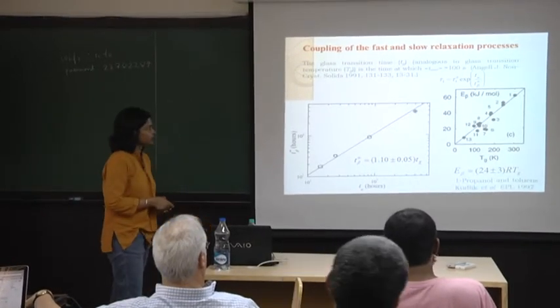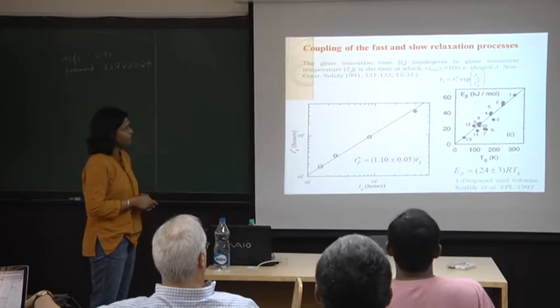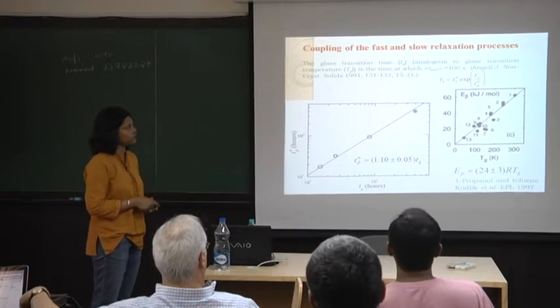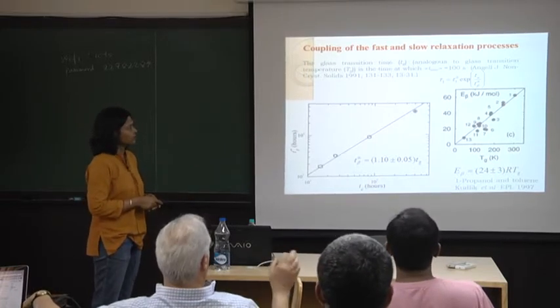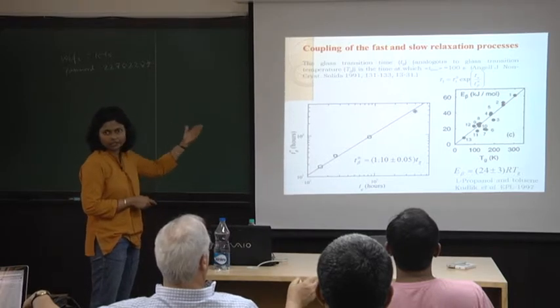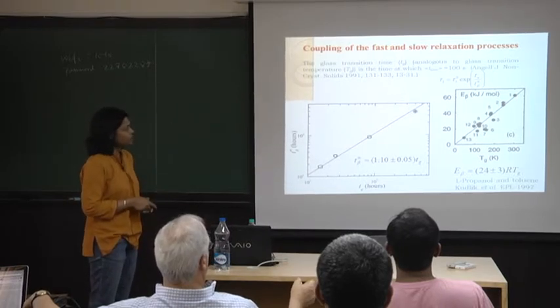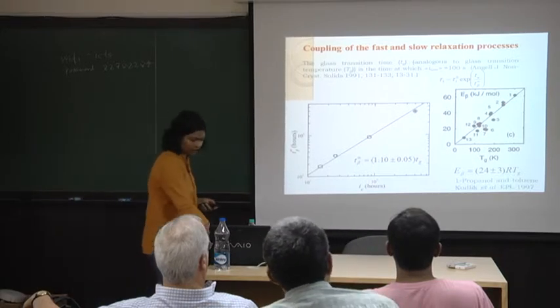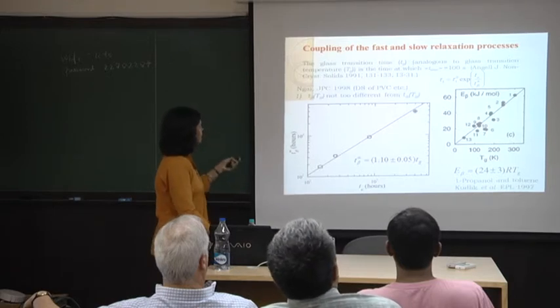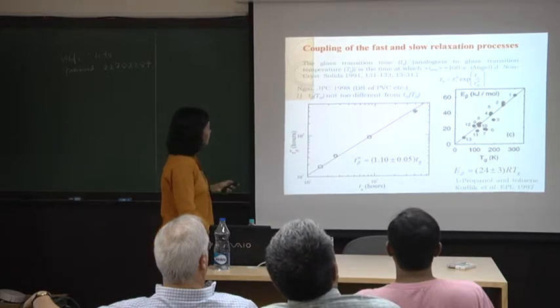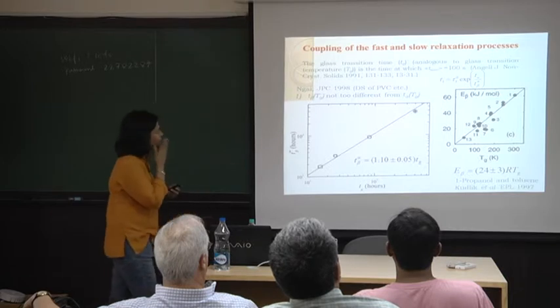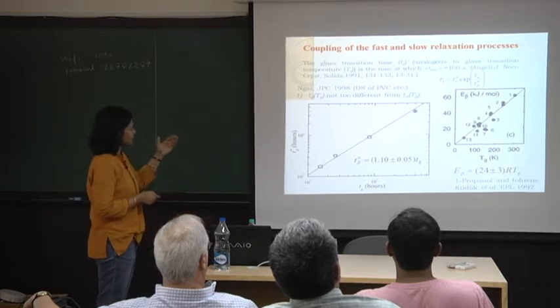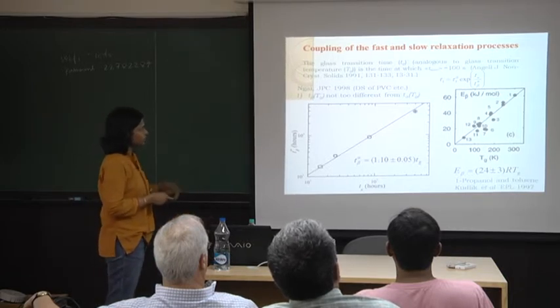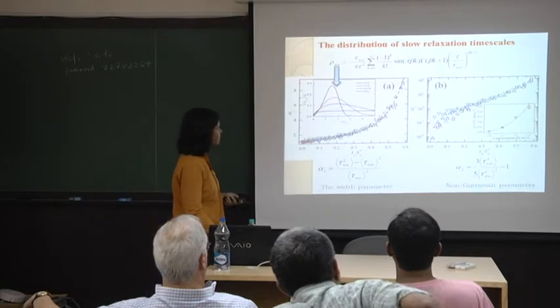So this is again a mixture of two organic liquids. They calculated, this was a dielectric spectroscopy measurement. They got the activation energy for the beta relaxation process out, plotted it versus the glass transition temperature, and they found a similar kind of a linear relationship. And again, there was this paper by Ngai in '98 where he did remark that the beta relaxation time is not too different from the alpha relaxation time at Tg.